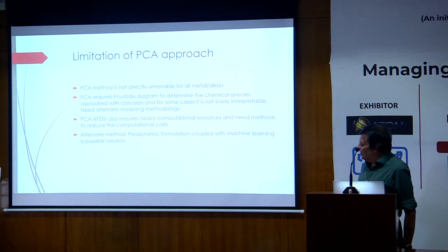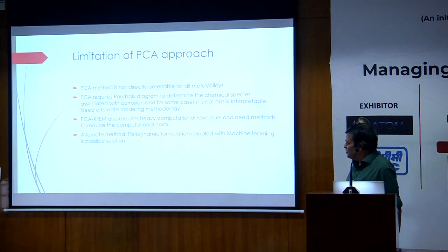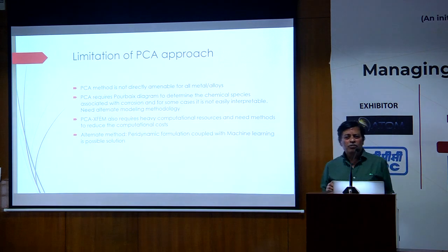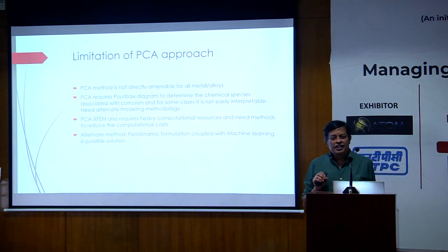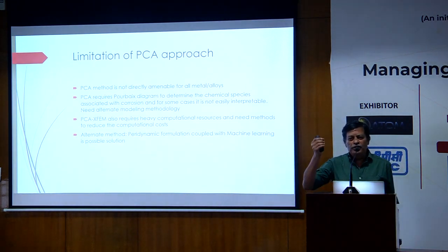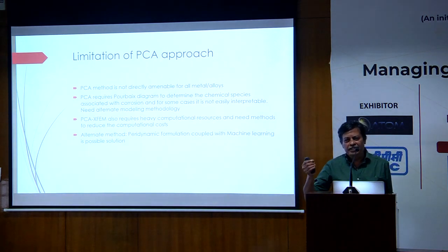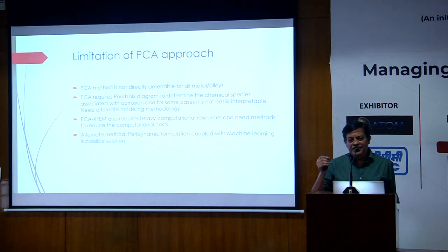So in order to do that, we went into a peridynamics formulation. Peridynamic formulation is an integral formulation. That means when you have a crack, if you try to use something like an FEM near a crack tip, there is a singularity solution, there are going to be oscillations, and the predictions near the crack tip will not be accurate. Whereas an integral formulation like peridynamics does away with that; you don't have to worry about singularity. That's the great advantage you have. But it is much more expensive than the regular FEM.